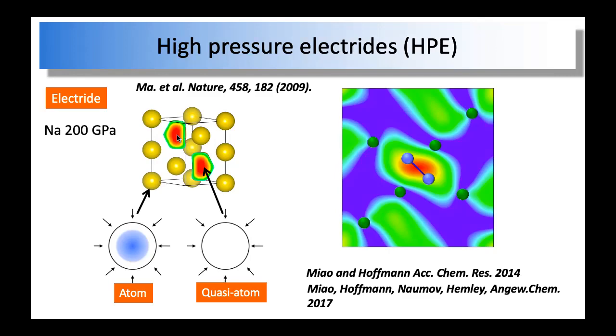The sodium sulfide, for example. It actually takes exactly the same structure as sodium sulfide under, I think, 16 GPa or something, right? And the theory that we propose is that really the open site can be represented by a local quantum orbital. And this local quantum orbital can start to take electrons, especially as its energy changes with pressure. And the energy level of this quantum orbital, what we call the quasi-atom orbital, relative to the atomic orbital, will change under compression.